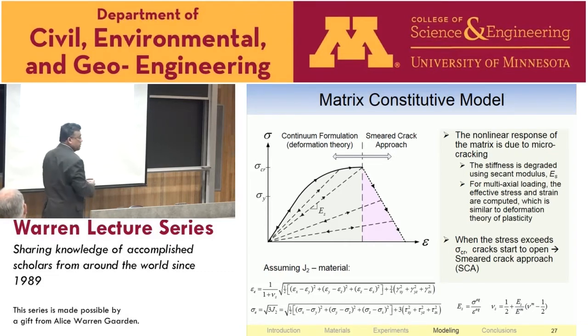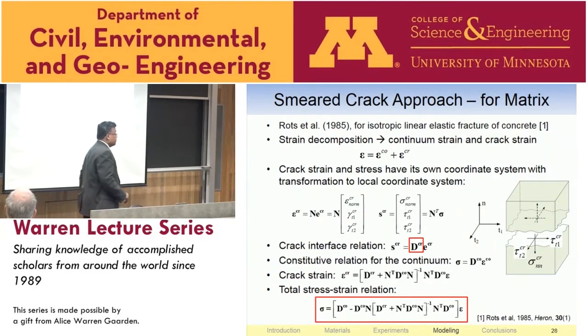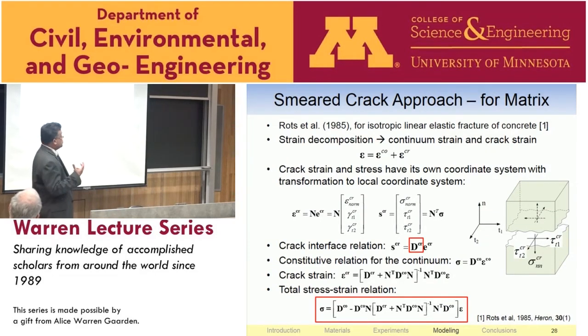And now the question is how you combine them within the same finite element framework. So we assumed it's a damaging material, so the instantaneous properties are the secant moduli and the shear moduli, and the Poisson's ratio, which we can get by knowing the equivalent stress and the equivalent strain for the material itself. And then we decompose the strain into two parts, the continuum strain and what we call a crack strain, right? And the crack strain is the strain that acts in the softening region, and the area under the traction separation law, which corresponds to the crack opening displacement, is your fracture toughness or your toughness. It's not really fracture, it's toughness because there's also damage in that region.